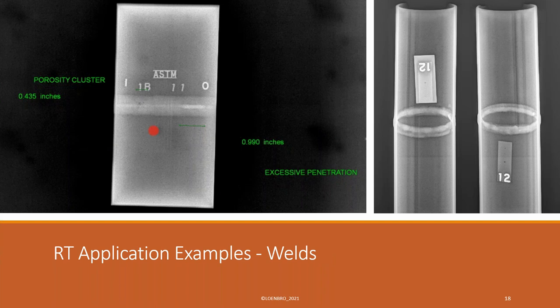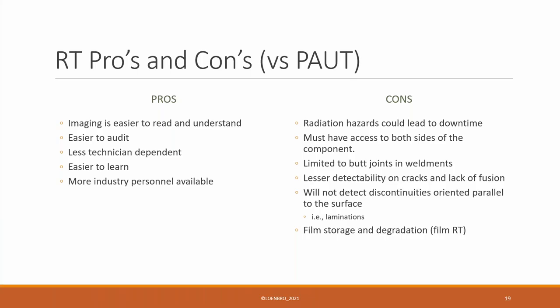And then obviously welds, probably the most widely used aspect of radiography. And you can see this is one of our general test plates here. You can see the density and the changes in density is what we're looking for. So if there's not enough material loss or air to provide a density change, the chances of you seeing it are slim to none. So you can see the multiple pores of porosity in the root bead here in the middle, you can see where there's some excess penetration there. So the light spot indicates that to us. A couple of girth welds, which is usually reserved to piping roughly three inches and less, smaller diameter piping. And these are digital, all these are digital radiography actually. And you can see how great the sensitivity. There's a hole penetrameter. You can even see the one T hole.